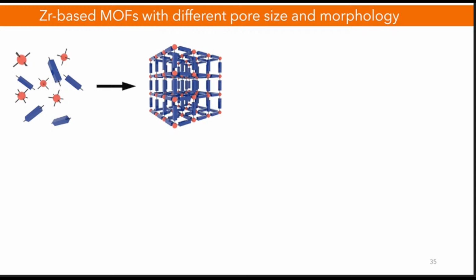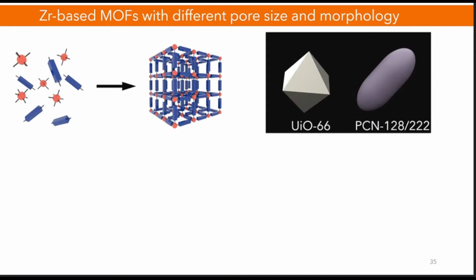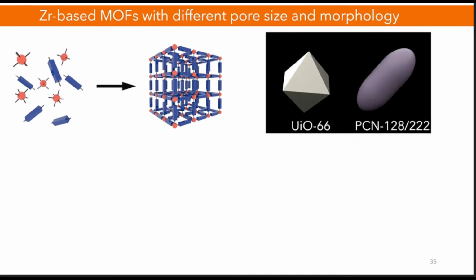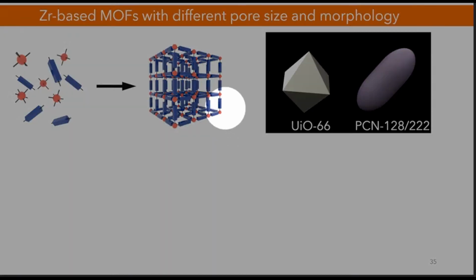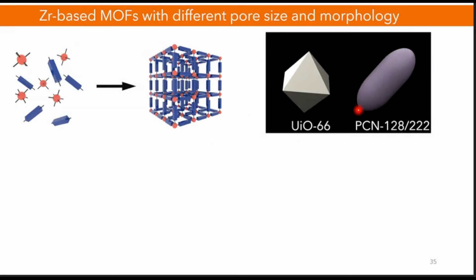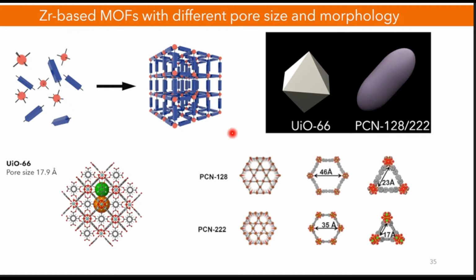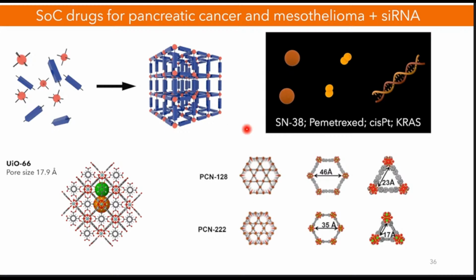We have been extending this, and we are interested not only in the simulation, as I said, but we also want experimental data where we can control the performance of all these different structures. For this, we focused on two top materials that we identified in our simulations. One is UiO-66, a material made of zirconium and BDC. Then we have PCN-128 and PCN-222, interesting materials with mesoporous cavities, basically the unidimensional channels that we are going to have in the porosity. Basically, we can load small drug molecules, cancer molecules like SN-38, pemetrexed, but also cisplatin, and we also have a lot of interest in different macromolecules, including this KRAS, which is going to be very important for example in pancreatic cancer.